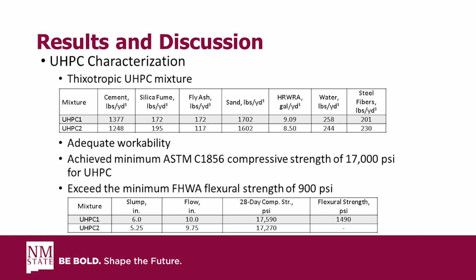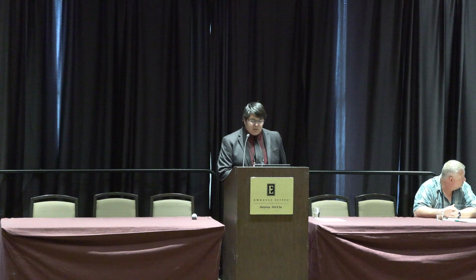And of course, we needed to meet that ASTM C1856 compressive strength of 17,000 PSI at 28 days, which we did with both UHPC mixtures, UHPC1 having 17,590 PSI, and UHPC2 having 17,270 PSI at 28 days. And we also exceeded the minimum Federal Highway Administration flexural strength of 900 PSI for that UHPC1, having a flexural strength of 1,490 PSI. Okay.